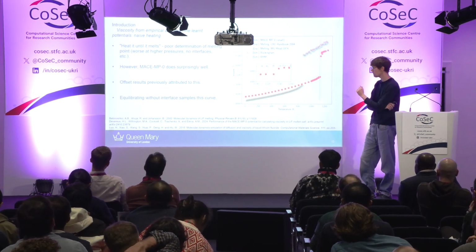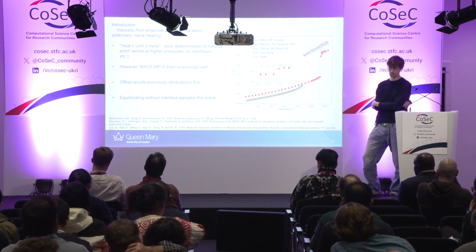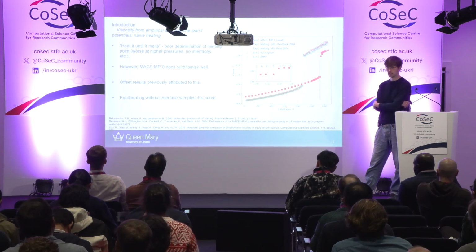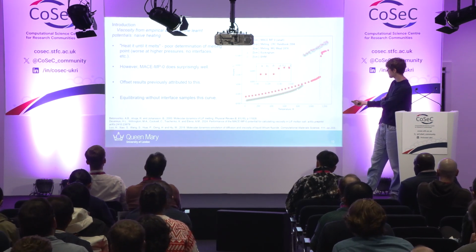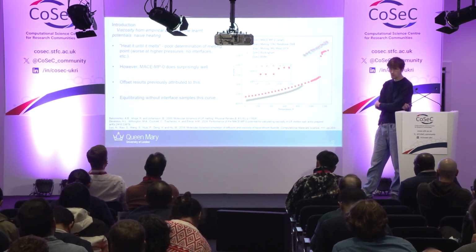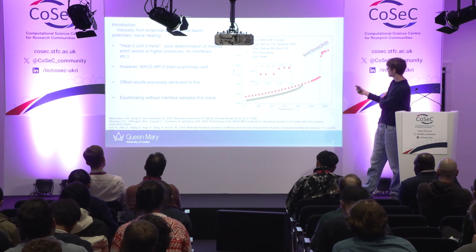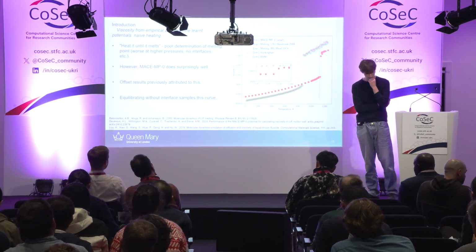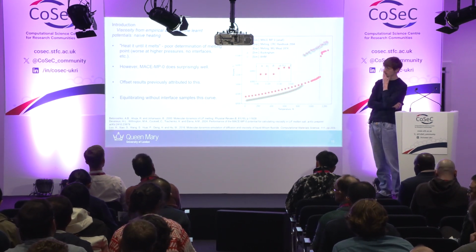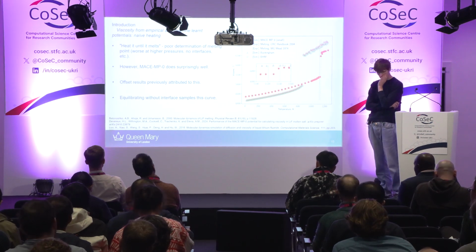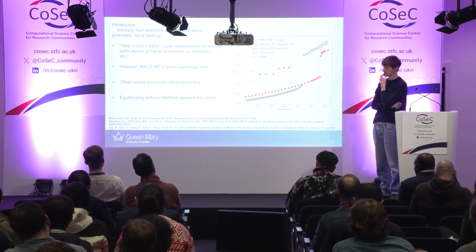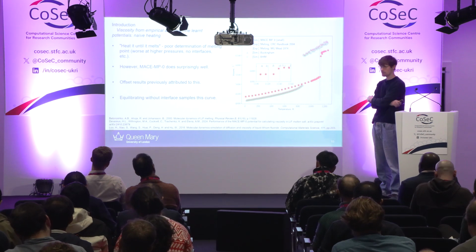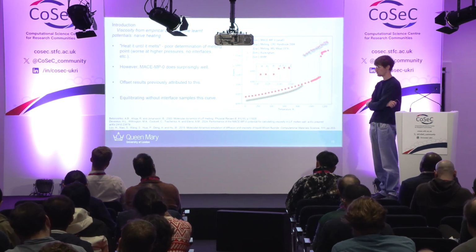It gives you a thermal instability, which may not coincide with the actual experimental melting point. As expected, the Buckingham and BHM potentials show this instability occurring quite a long time before the experimental melting points at atmospheric pressure. Whereas for the MACE model, surprisingly, the instability occurs at the melting point, which is surprising given the difficulty of accurately determining melting temperatures in MD. We don't have any interfaces or other more accurate methodologies going on here.